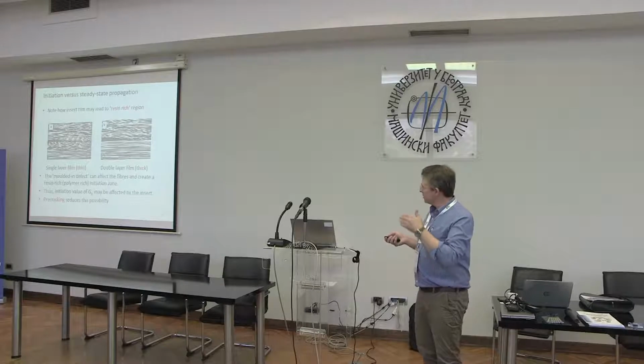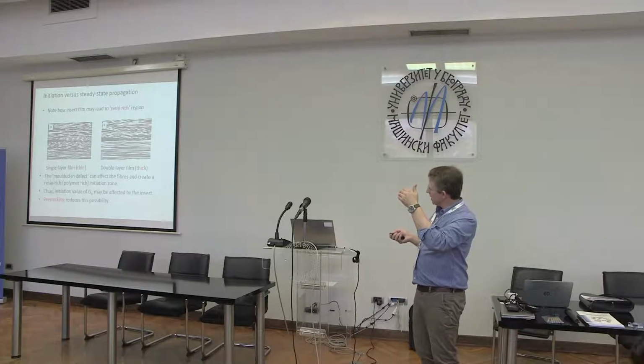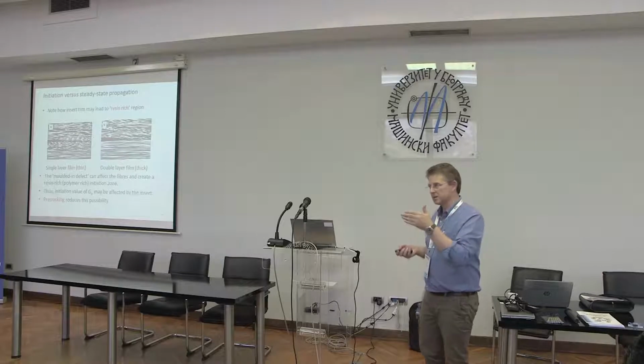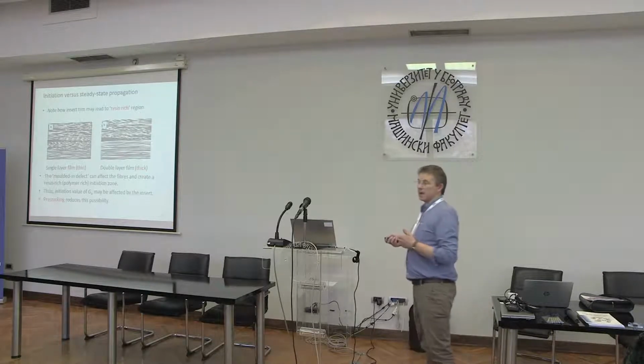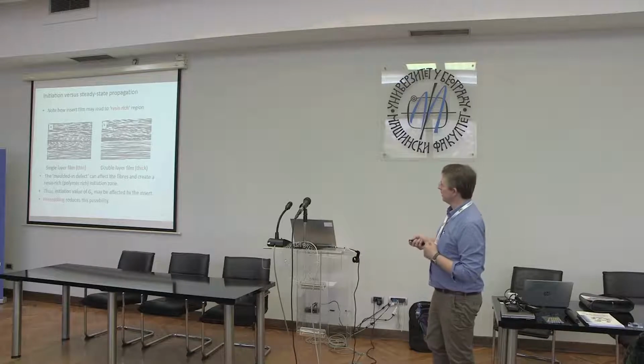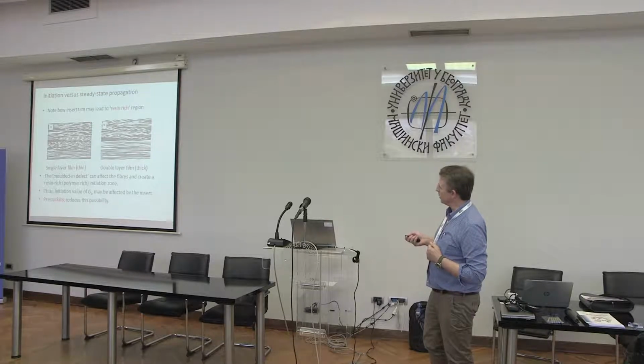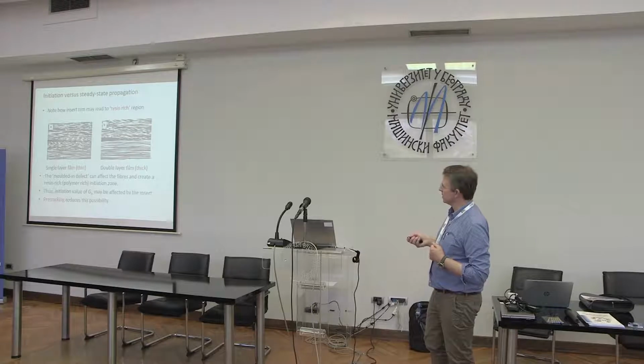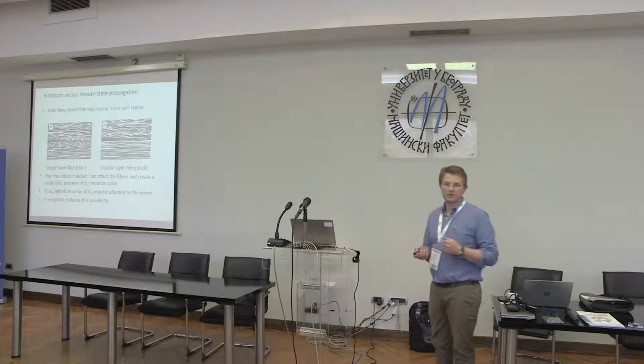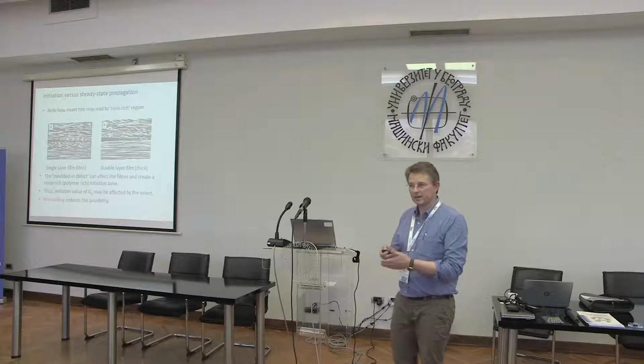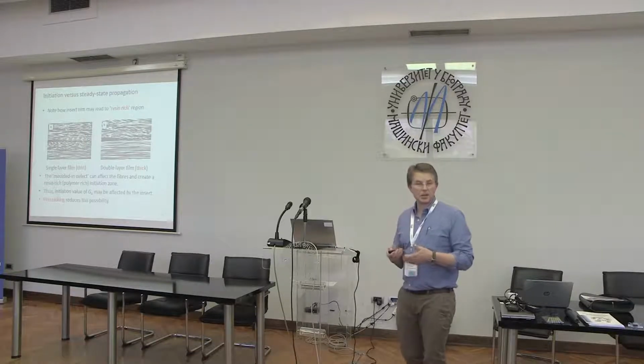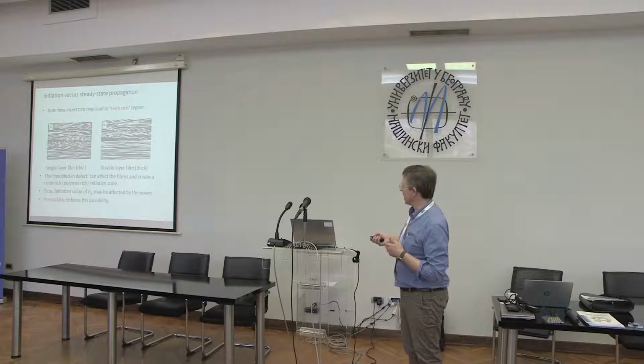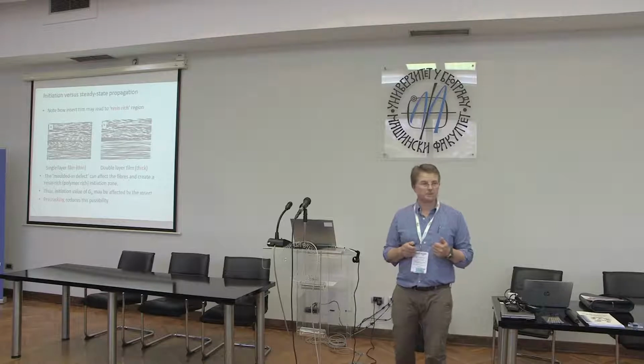So these were some micrographs taken by polishing the side of the specimen at the end of the insert material. And what it showed quite nicely is that if you use a single layer of film, you can see the extent to which the fibres are displaced around the film. So of course the thicker the film that you embed, the more fibre displacement you have and the more potential you have for what's described as a resin-rich pocket to form at the crack tip.